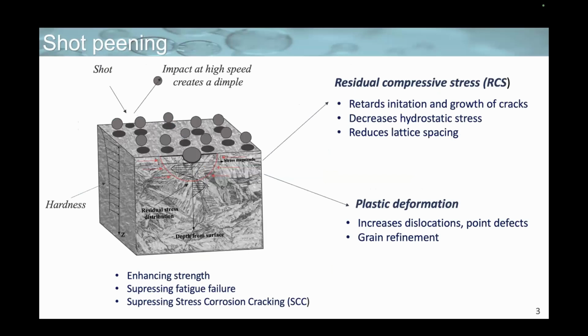So shot peening is a mechanical surface modification where a stream of shots, which can be of different materials like ceramics, glass, steel, impact the substrate surface. This results in two effects. First one is residual compressive stresses, and second one is plastic deformation. When talking about residual compressive stresses, they retard initiation and growth of cracks, decrease hydrostatic stresses, and reduce lattice spacing. All of these three points are very desirable to combat hydrogen embrittlement of high-strength steels. On the other hand, plastic deformation increases dislocations, and dislocations can act as hydrogen trapping sites. And also it induces grain refinement.